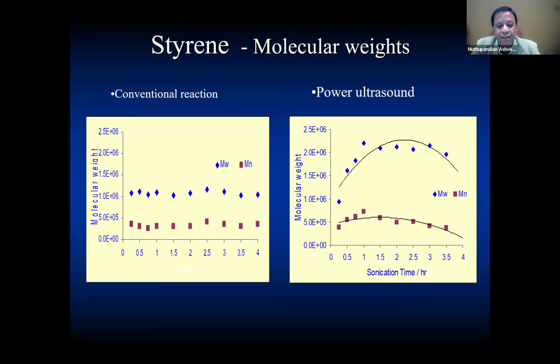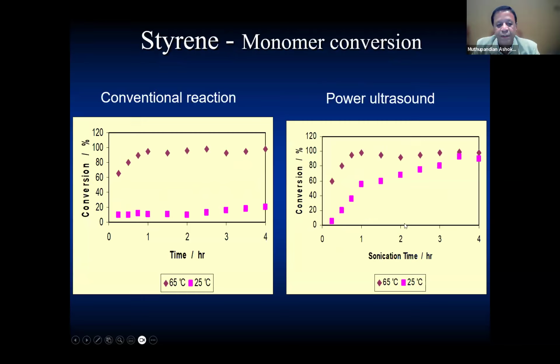So the polymer industry has a large economic play in every country. When they try to synthesize polymer, they need to make sure that the molecular weight of the polymer remains constant throughout the reaction time. So if I'm going to replace the conventional method using the ultrasound method, I need to make sure that the molecular weight does not change as a function of reaction time. You can see that pretty much from 0.5 to 4 hours, the molecular weight does not change.